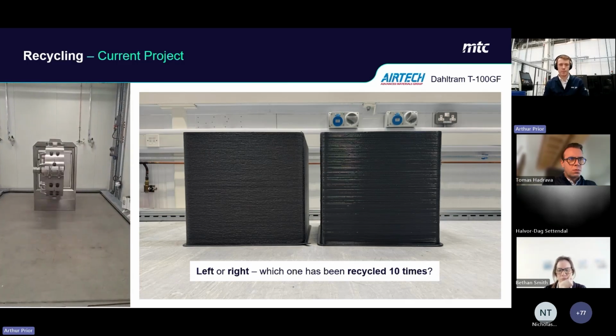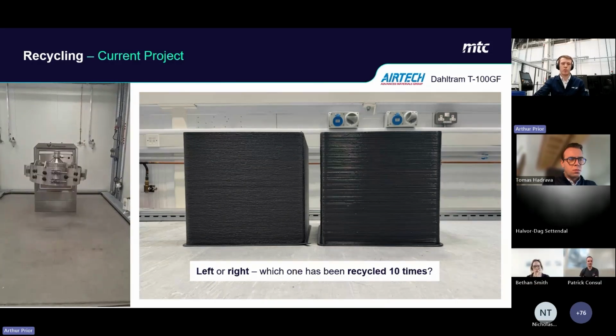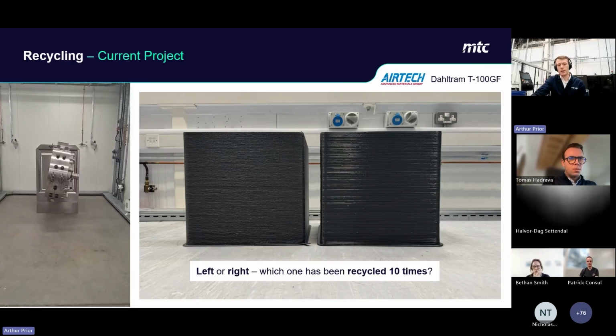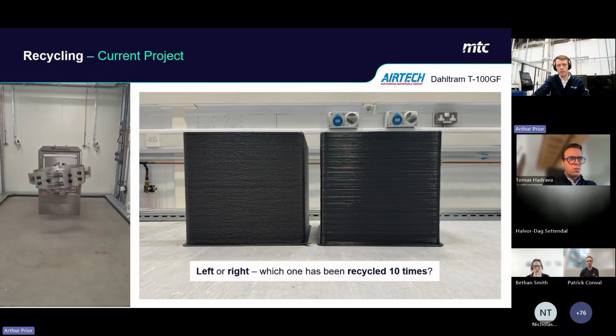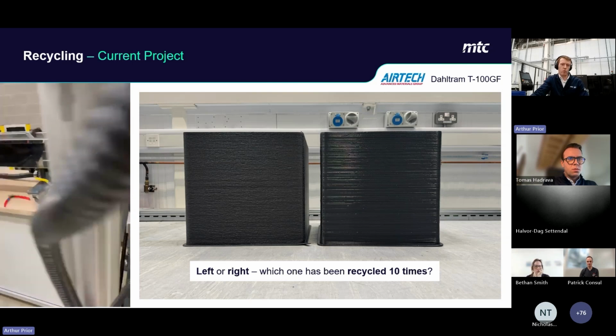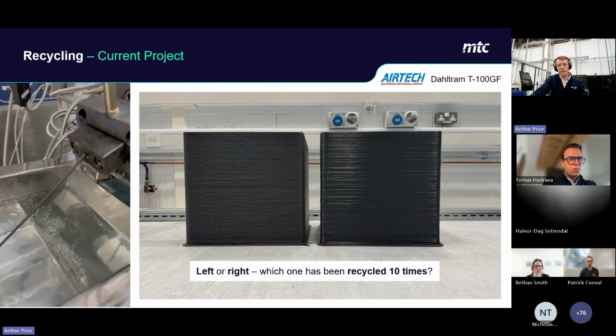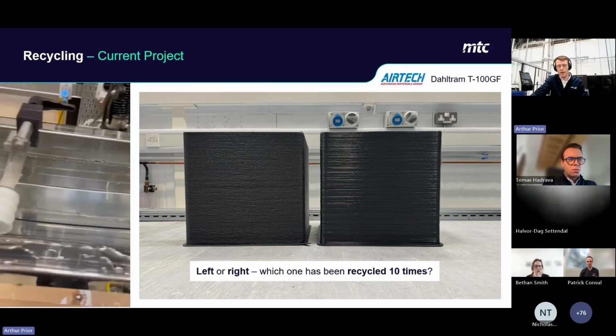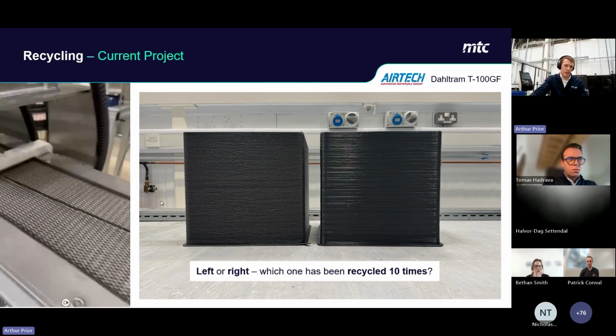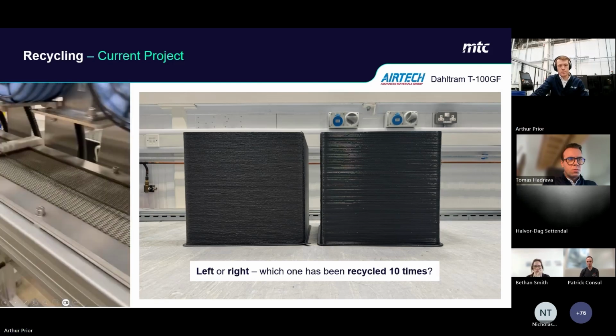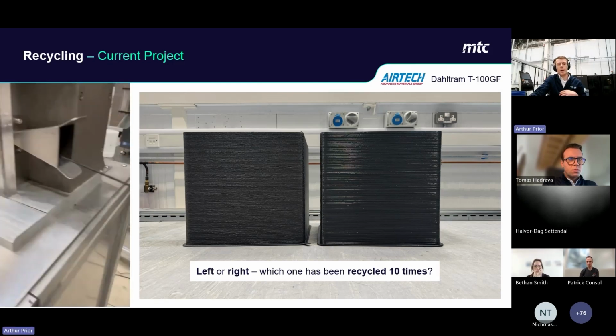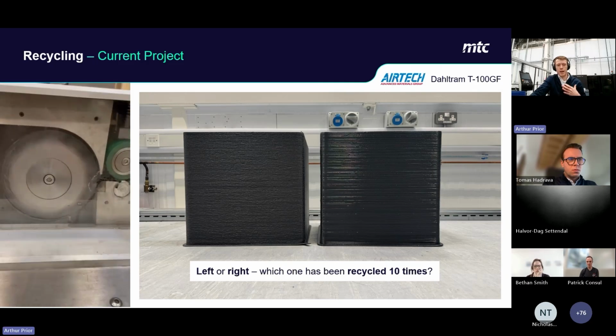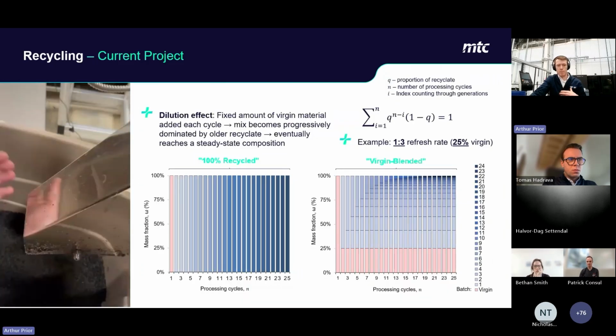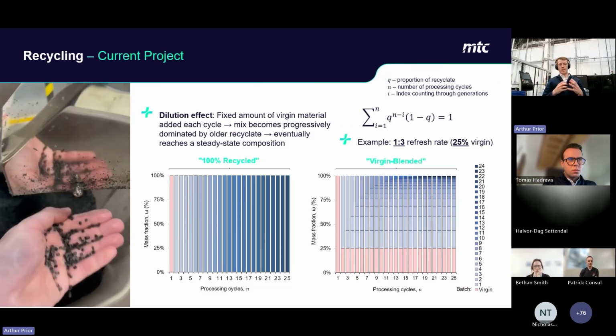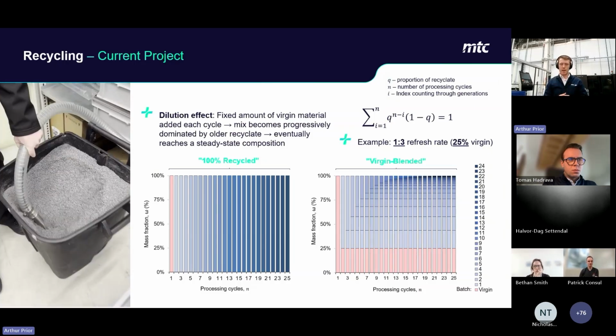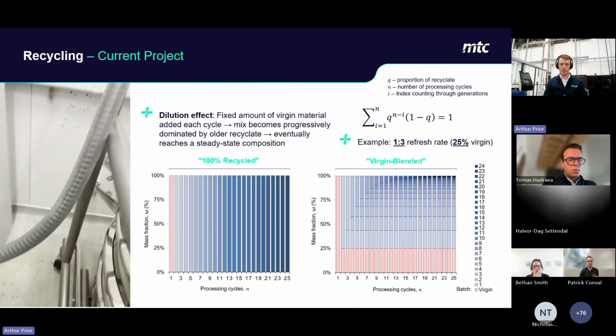patterns with this material. So our experience is that if you control the recycling process correctly, then actually with some minor equipment modifications, you can print directly using regrind, meaning that you may not need to repelletize the material after granulation, as you can see here in this video. So in this case, a key goal of the project is really looking at how we can actually blend virgin material and regrind to really find the optimal refresh ratio needed to maintain, let's say, acceptable material properties.